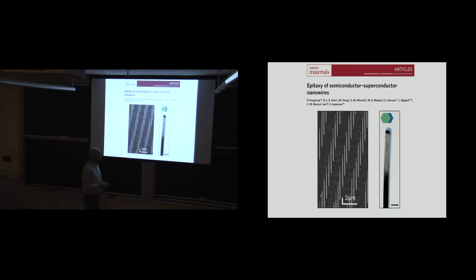Here's the wire, there's the gold ball catalyst at the end. And in the same MBE chamber, molecular beam epitaxy chamber, where he was growing these wires, he stopped the growth and he turned on the aluminum gun inside of the MBE chamber. And he got the temperature just right so that the aluminum neither went down and stuck, nor did it do what it would do at high temperature, which would be ball up, because the aluminum likes itself more than it likes anything else. But find the right temperature, the right pressure, the right evaporation rate, and a remarkable thing happens.